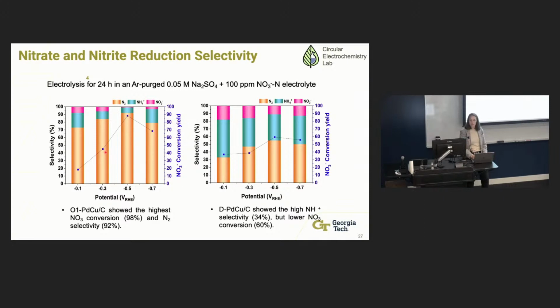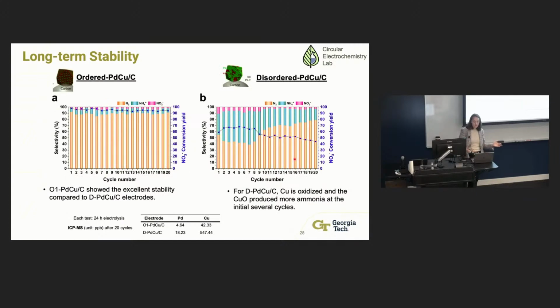Again, you can see clear differences. These materials have the same atomic percent of metals in them. They are both alloys, but very different product selectivity, whether you have a disordered catalyst or an ordered catalyst. Most notably, with the ordered catalyst, we're getting nearly all nitrogen production. And with the disordered catalyst, we're getting a wide variety of products, a mixture of ammonia and nitrate. Again, we look at long-term stability, and the ordered catalyst seems to be very stable.